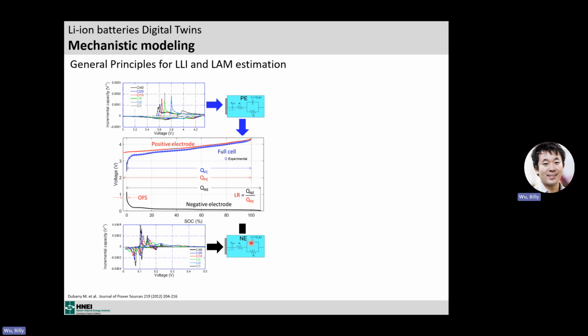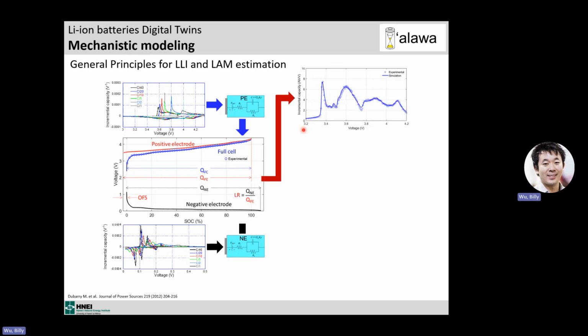Now the next step is to match the full cell response. So we can play with 2 parameters, mostly, at low rate. The size of one electrode compared to the other. Which electrode is bigger than the other? We can look at the ratio. That's the information we need, the ratio of capacity, positive versus negative. And we need to look at their offset. That's pretty much how much lithium was lost during formation. And if you play with that, and if you play with the rate on the electrode a little bit for kinetics, you can match really well the full cell and the difference of the half cells.